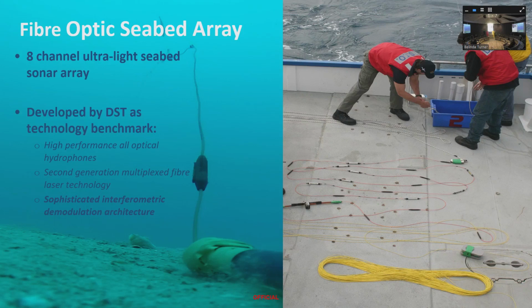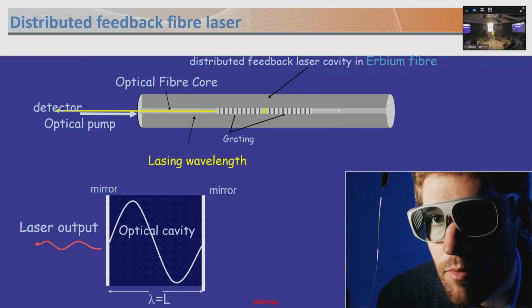So I just want to come back to this fibre optic sensor that I showed earlier in the presentation. Each of those silver blobs in the picture on the right-hand side is a fibre optic hydrophone, and inside that is something called a distributed feedback fibre laser. This is a sensor that works on a completely different principle, totally different. What it is, basically, is a very small amount of erbium-doped fibre. So it's an active fibre. It's a fused silica fibre that's been doped with a rare earth called erbium.